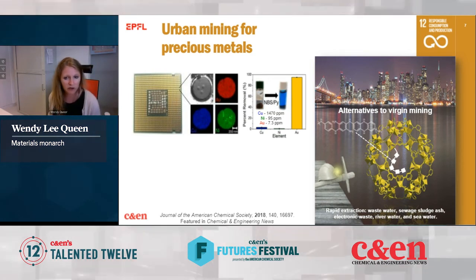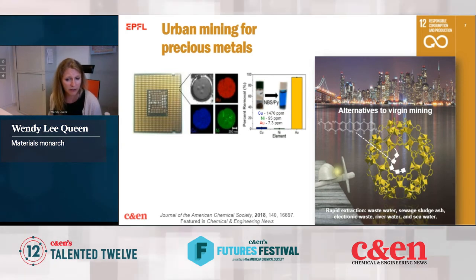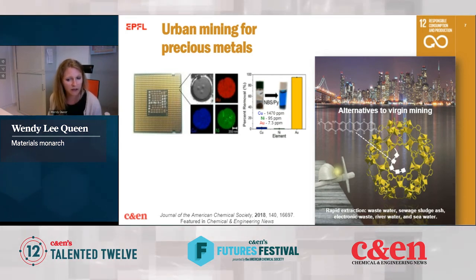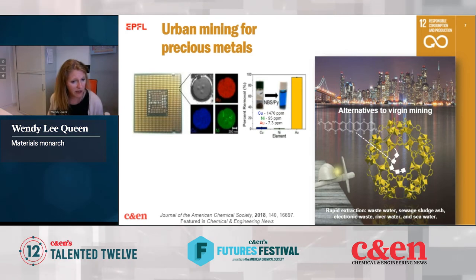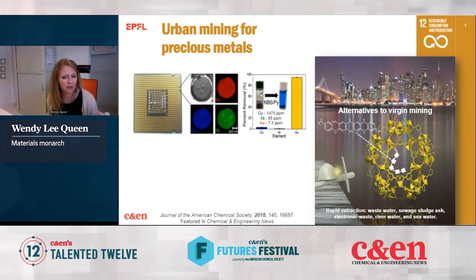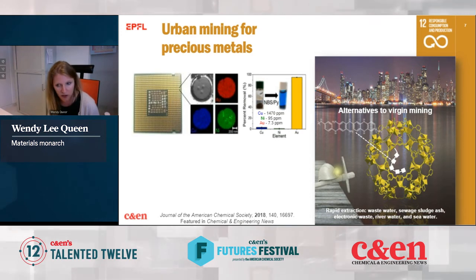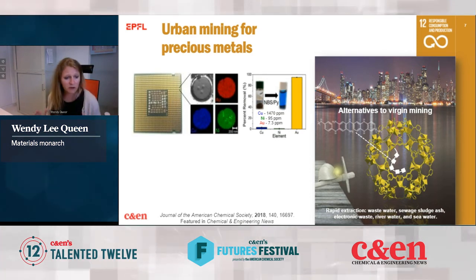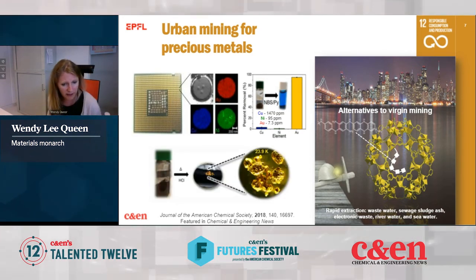Okay, so what I'm showing you here is that we can selectively extract the gold and leave behind the copper and nickel. And I note that the copper has a concentration that's 200 times that of the gold. And despite this, our material still selectively extracts the gold. We can basically then concentrate that gold inside.